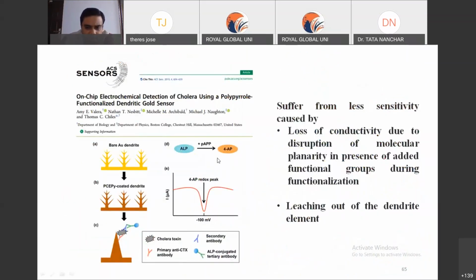This is another recent report from 2019, in which we developed the bare gold dendrite electrode. The problem whenever you use a metallic surface for the analysis of any protein is that it has a tendency to adsorb onto the surface. That is the reason we incorporated chitosan in the system, because in our experience it did not allow that kind of fouling. That was the plot of our investigation in this work.